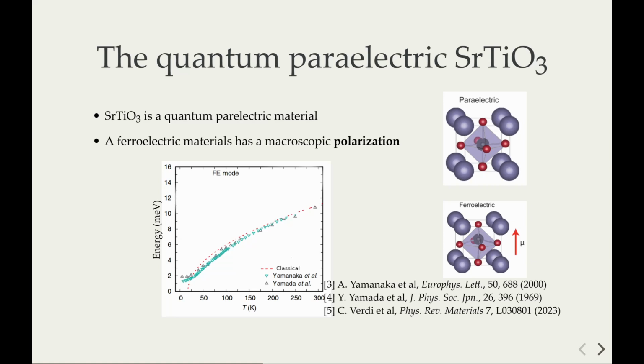phonon mode that drives the ferroelectric instability, it goes down with temperature following the Curie law, but then at a certain point, it deviates from the Curie law and saturates, never reaching 0. When this reaches 0, we have the ferroelectric transition. So this material never reaches the ferroelectric transition, but saturates. This saturation is given by the fact that quantum fluctuations of the oxygen atom, in this case, stabilize the paraelectric phase.